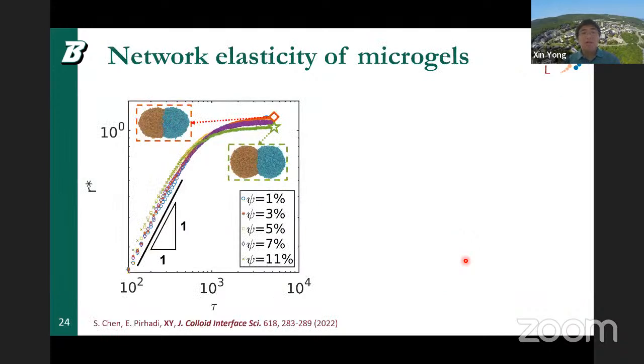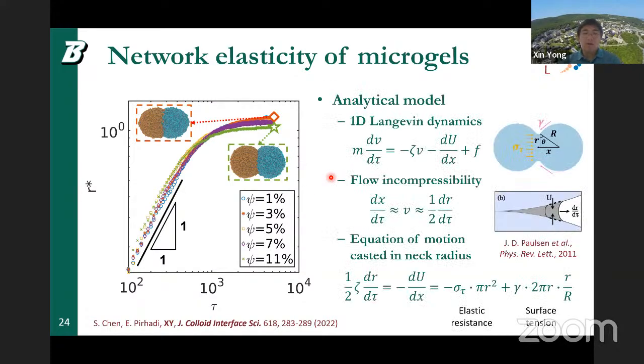We're also looking at the effect of network elasticity by changing the cross-linker density of the microgel. And we can see here, this doesn't change the initial dynamics. The late dynamics very clearly change due to the variation of elasticity. So the final steady state neck radius is much smaller when you increase the cross-linker density. Because the initial stage is much better understood, we want to understand more of the late stage, where apparently the elasticity and viscoelasticity play the role. So we developed an analytical model to try to describe this neck evolution in this late region.